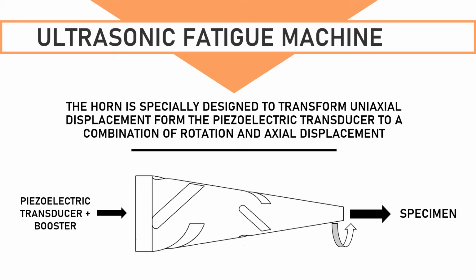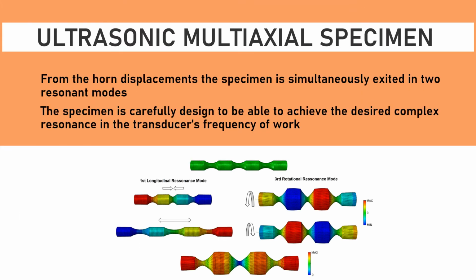The horn receives axial displacement from the piezoelectric transducer that transmits to the booster, that transmits to the horn, and this axial displacement is then transformed partially to rotation and axial displacement. From the two displacements transmitted by the horn, the specimen is then excited in a complex resonance mode composed by two modes that we specially designed to be within the range of frequency of work of the transducer. These modes are the first longitudinal mode and the third rotational mode. These were chosen in order to have one region with higher tension torsion stress.